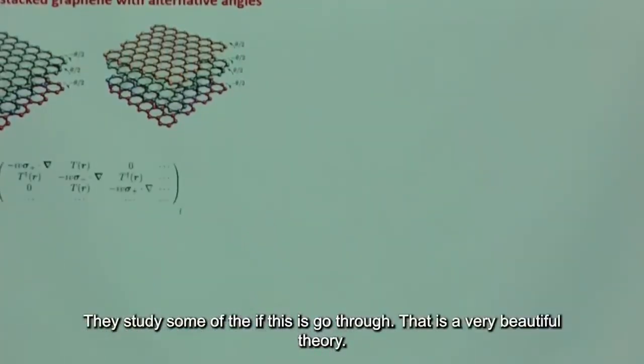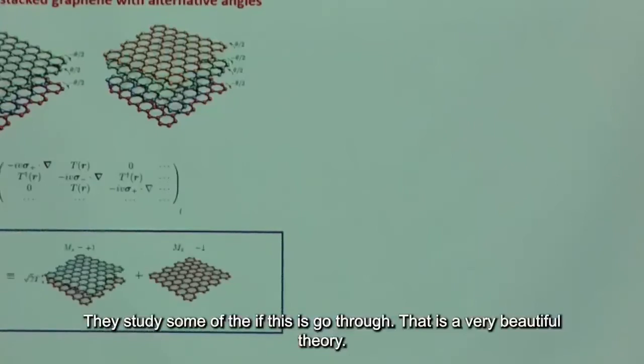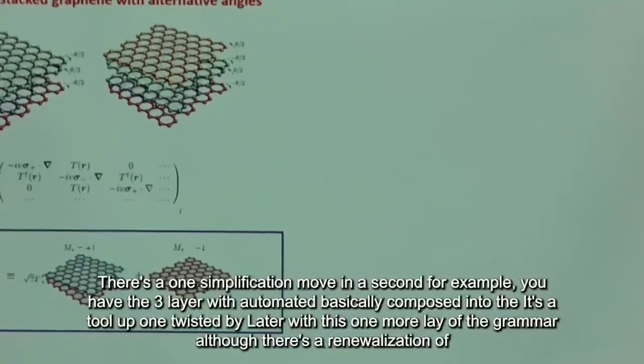It turns out, if you go through this very beautiful theory, there's one simplification one can make, at least if you look only at the low energy sector. For example, if you have a 3-layer structure with alternating stacking angle, it basically decomposes into one twisted bilayer together with one monolayer of graphene. Although there's a renormalization of the twisting angle, the stacking, the interactions considering this twisting angle.